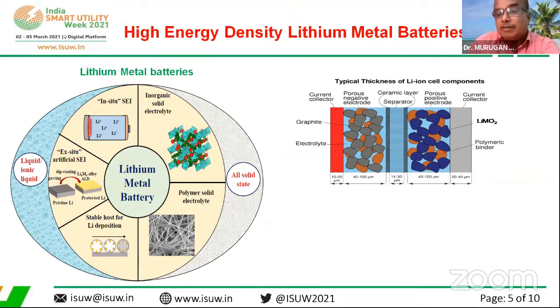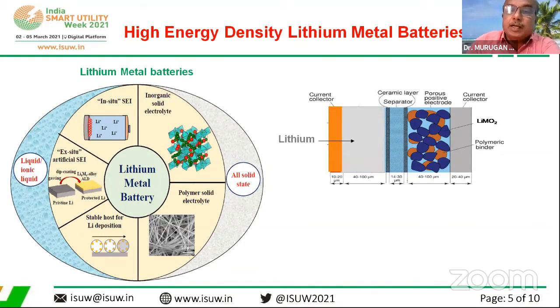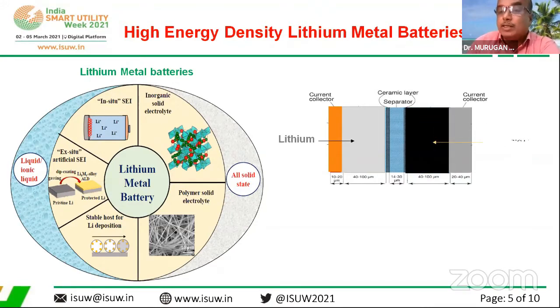So we have the graphite and the lithium cobalt oxide, lithium iron phosphate, whatever the insertion electrodes, in between organic electrolytes. So we just need a separator. We can replace the graphite by means of lithium metal. This is what we want. And replace the conventional insertion electrode by anything you want, starting from LCO to NMC, NCA, add sulfur. If someone is able to find new electrodes, it's quite interesting that we can also have them.